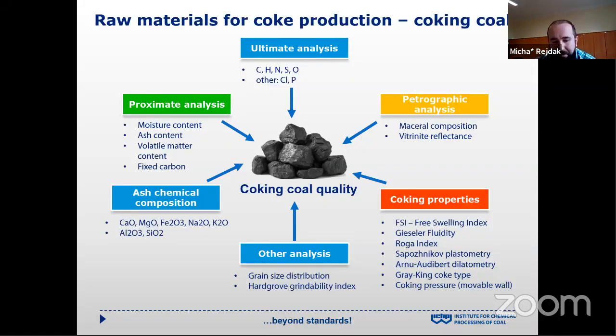Very important parameters are the Gieseler plastometer and Audibert-Arnu dilatometer tests. These tests in general monitor how the coal behaves as the different macerals melt, devolatilize, and resolidify at different temperatures during the carbonization process. The Gieseler plastometer evaluates the coal behavior by measuring the fluidity of a packed coal powder as it is heated, whereas the Audibert-Arnu dilatometry measures the contraction and expansion of the powdered sample pressed into a cylindrical coal pencil. These properties are important to classify coals and of great relevance when different coals are to be blended for coke production, to of course ensure compatibility of the different blend components.